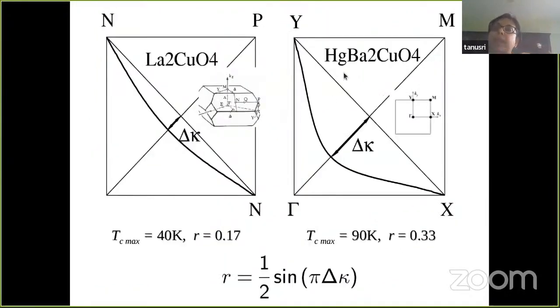If you really look at the Fermi surface of these two compounds that I mentioned, the lanthanum cuprate and the mercury cuprate, the Fermi surface of the mercury compound is much more rounded, while in case of the lanthanum compound, it's much more squarish. That's just from the photoemission data that shows in the overdoped regime of this cuprate. And this is the Fermi surface calculated from the density functional theory, and one can define a delta K.